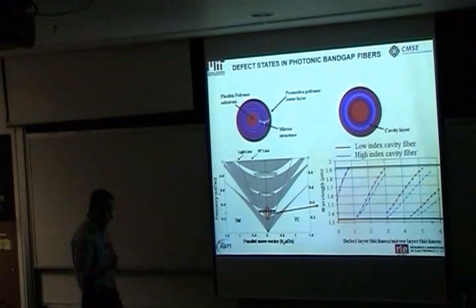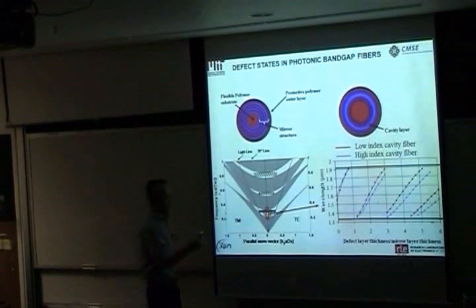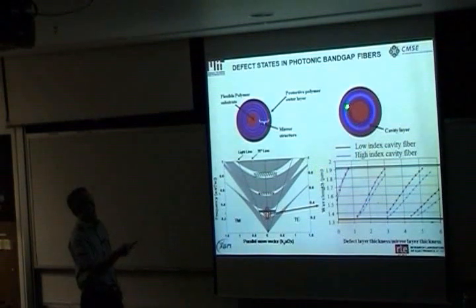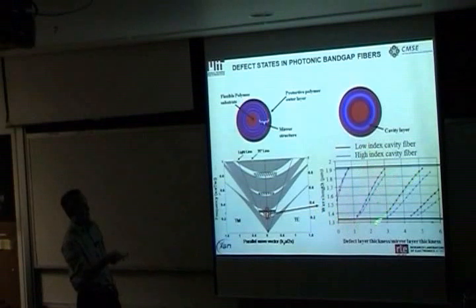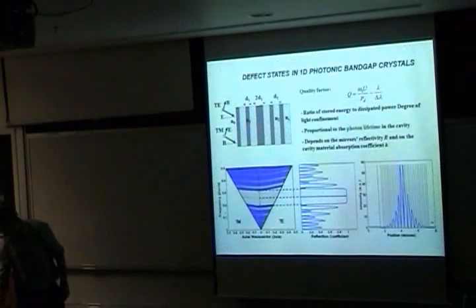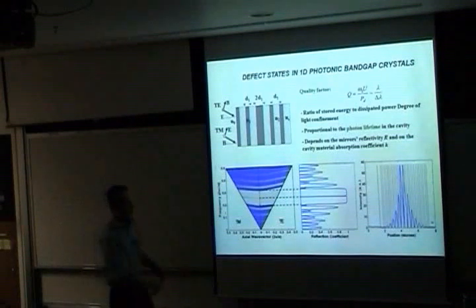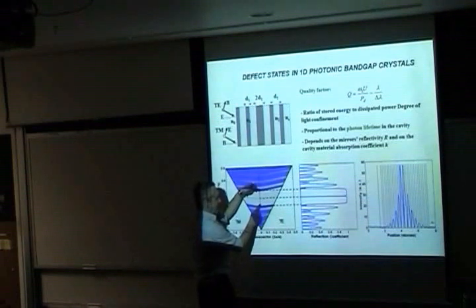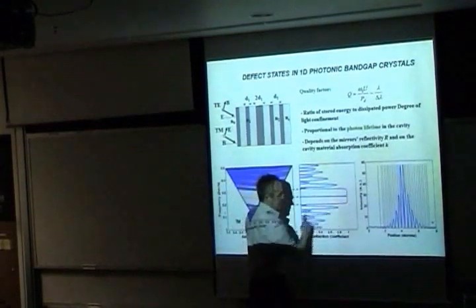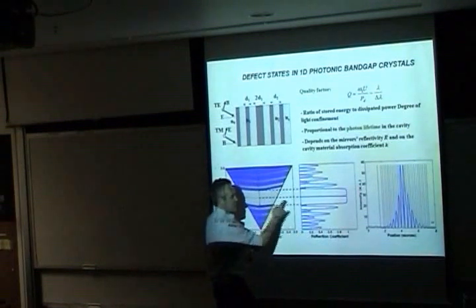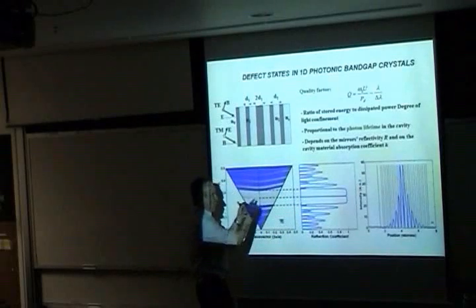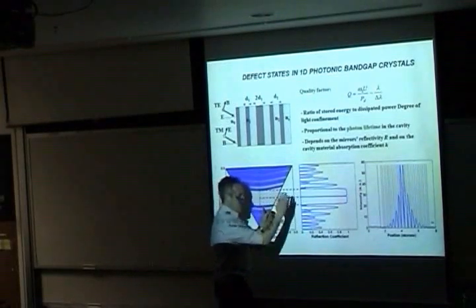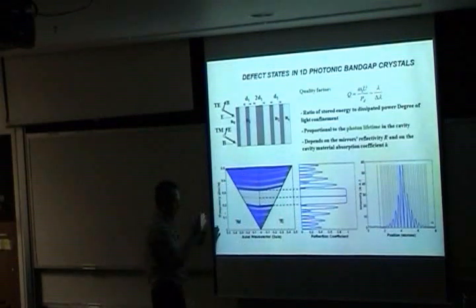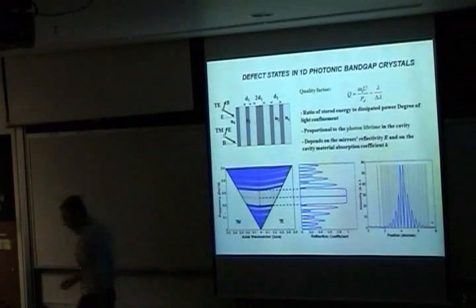What happens in a semiconductor when you create an imperfection, those imperfections generate localized states within the band gap, and in fact that same thing would happen here if we created an intentional imperfection in these otherwise periodic structures. We'd actually get within our band gap a localized mode. And this localized mode, the way you'd measure it is actually take a reflection spectra. The band gap would just give you a very broad reflection. This is a reflection coefficient as a function of frequency. So it would give you a very broad reflection. However, once you have a defect in your structure, you get a very sharp transmission line. And the sharpness of that transmission line actually relates to how localized that mode in fact is.